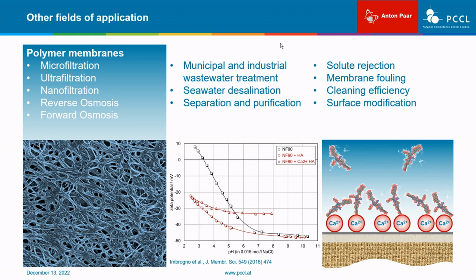In the presence of a combination of humic acid and the divalent calcium ion, we realize another effect on the Zeta potential of the nanofiltration membrane. The isoelectric point remains unaffected, but the magnitude of the Zeta potential decreases further, which we may explain by an increase in the surface of the membrane that is covered by humic acid. We can imagine that the calcium ions act as a bridging link between the negatively charged membrane and the negatively charged humic acid molecules.